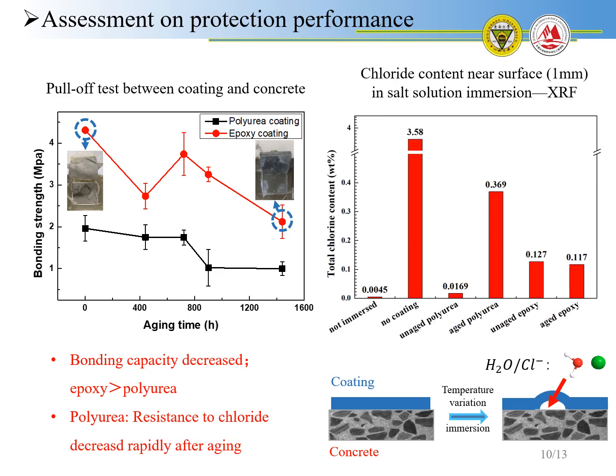From the salt solution immersion results, first we can find that either coating can significantly reduce chloride ingress by at least one order of magnitude, while the epoxy resin doesn't change too much after aging. For polyurea, after aging, there is a sharp increase of chloride content, almost 20 times. This is because the water passed through the polyurea coating and accumulated at the interface area, leading to continuously weakening performance.